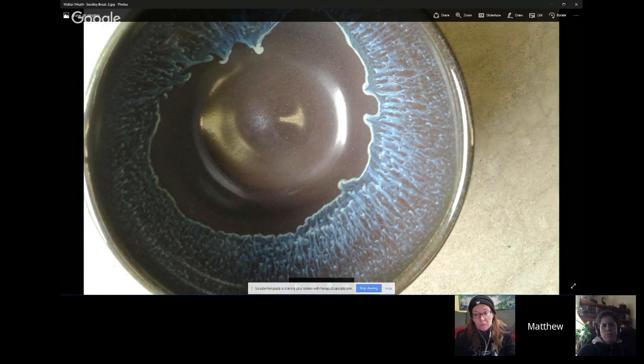And what that's doing is that the boron can't find a home in the glass. So in our glasses, we still have this condition of there are only so many open spots to insert a boron molecule and to insert a fluxing molecule. Because going back to how our fluxes are working, they come in and they break an oxygen to silicon bond, right? And the problem is there's only so many of those. Although there's a ton of silica in a glaze, there is still an absolute finite number of those bonds that you can break. If you overload the system, it can no longer insert itself.